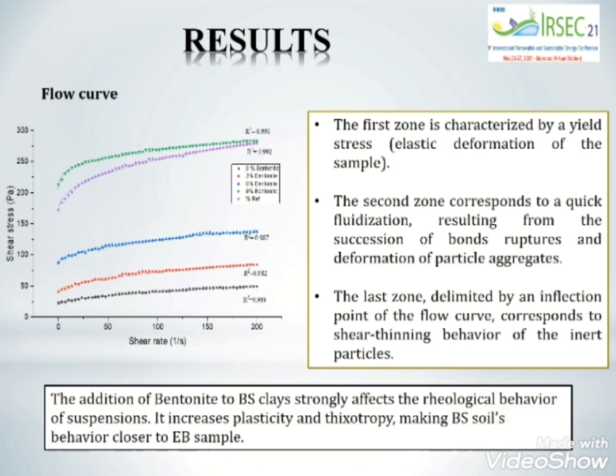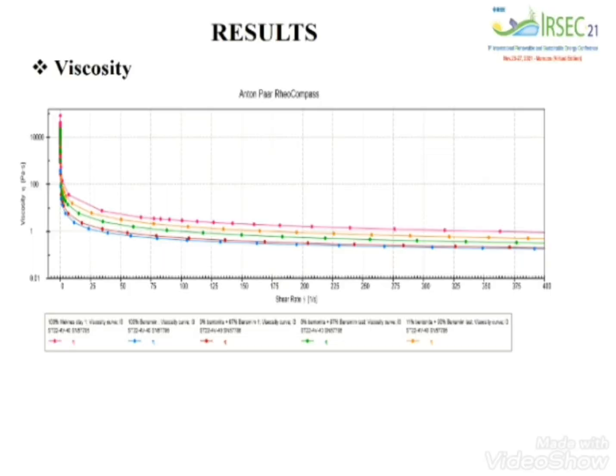The addition of bentonite to Bensmim clay strongly affects the rheological behavior of suspensions. It increases plasticity and thixotropy, making Bensmim soil's behavior closer to the reference sample. On the other hand, we can see that the viscosity of all studied suspensions decreased with increasing shear rates, and we can say that it became steady at higher shear rates.